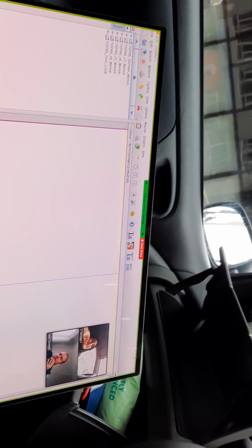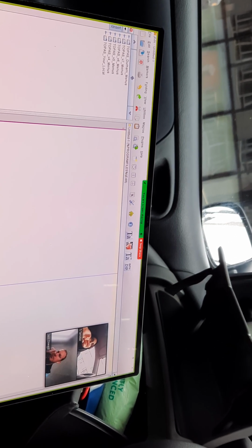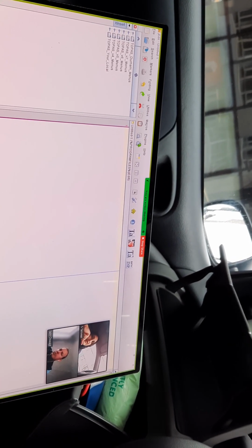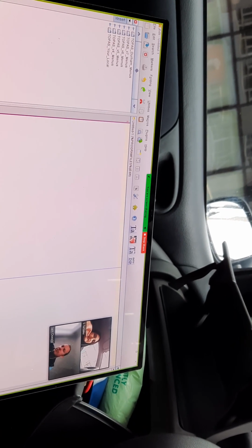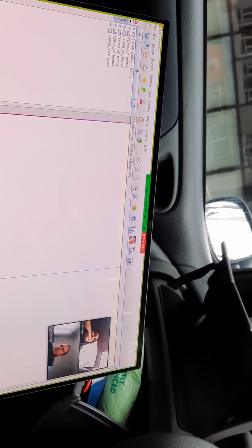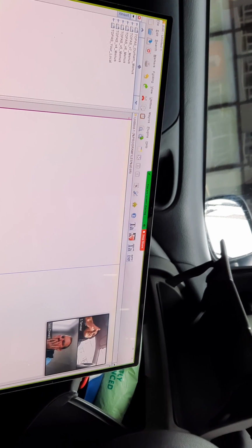So I requested Martin if he could do the single crystal. From the unit cell parameters, Martin found that it's basically a solvate of ethanol, a miconazole solvate with ethanol. Today I did the DSC of it. From the endotherms I would be able to see at what temperature, since it has ethanol, I can heat it up or evaporate it, get rid of the ethanol, and then get the free base.